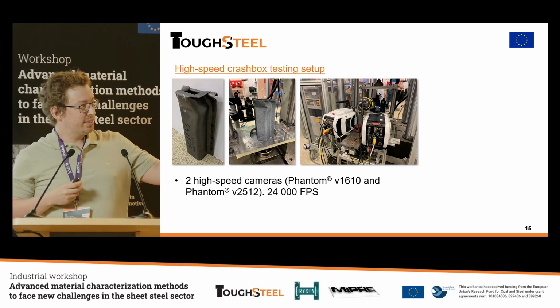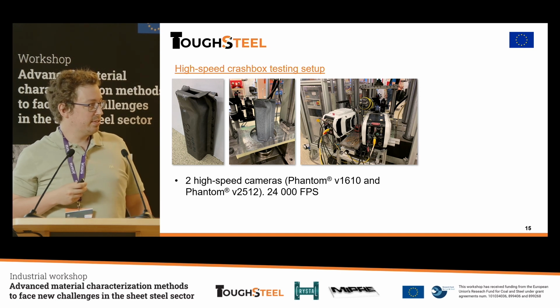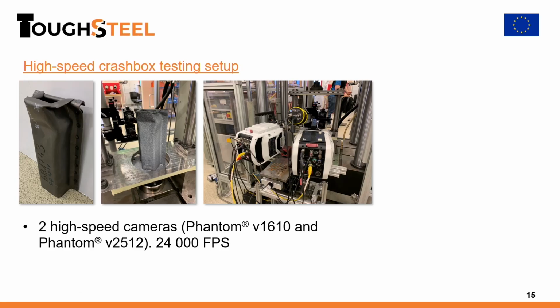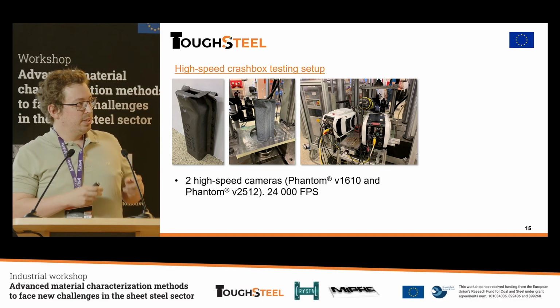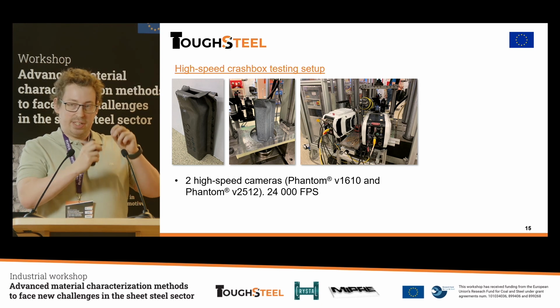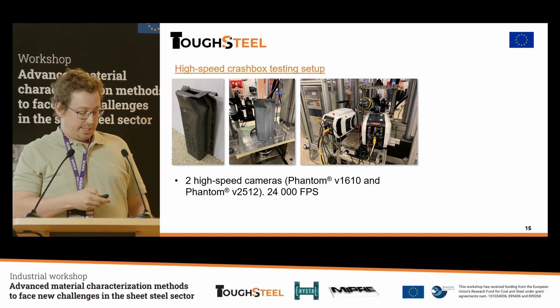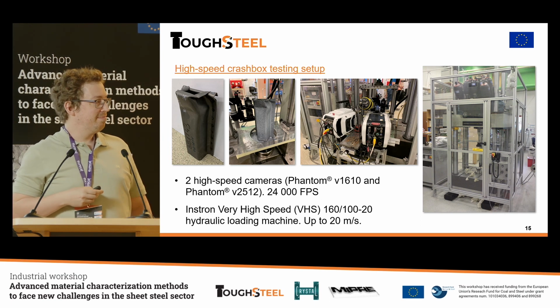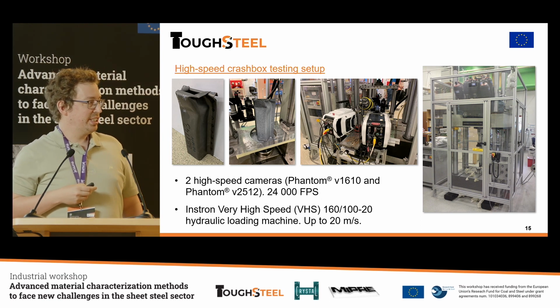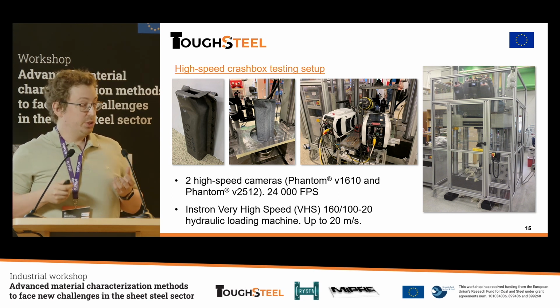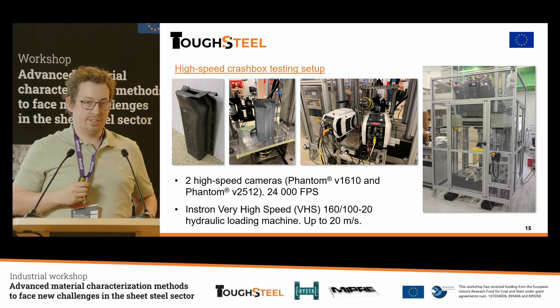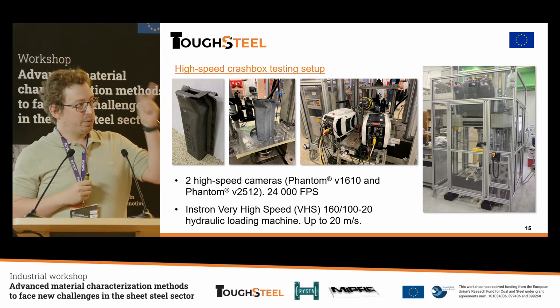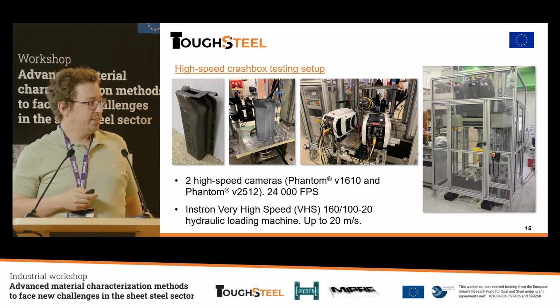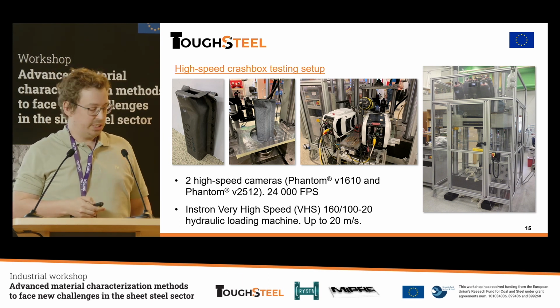We speckled it and used stereo high-speed cameras. So you can see I have Phantom V1610 and 2512, and tried to do a stereo DIC measurement to capture the whole deformation from start to finish, and try to identify when the cracking happens and how to measure it. And instead of a drop tower, we had an Instron very high-speed machine. It's a hydraulic loading machine, and we use this for tensile testing a lot, for pulling characterized materials at high strain rates. But we can also use it in compression, which we did here, and it's able to reach speeds of 20 meters per second.